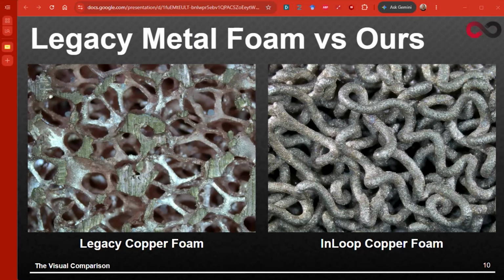Whereas if you put InLoop Foam into tension, the actual coil bent structure will first unbend, and in doing so absorb more energy before entering the state where those links are then straight, where legacy copper foam begins. And so we're able to absorb a lot more energy in that tensile regime. And then there's also some interesting relationships on how that relates in compression as well. But functionally, the actual differences are coming from the microstructure between the legacy processes and ours. And this is what that generally looks like.